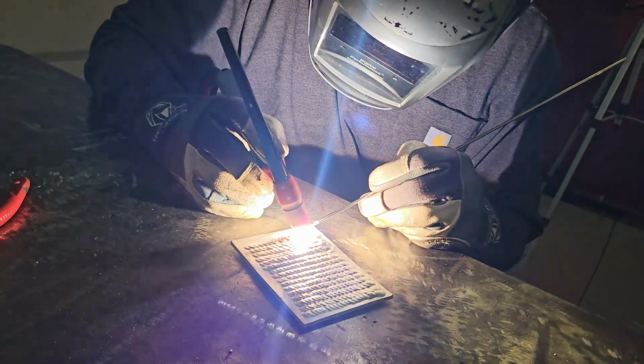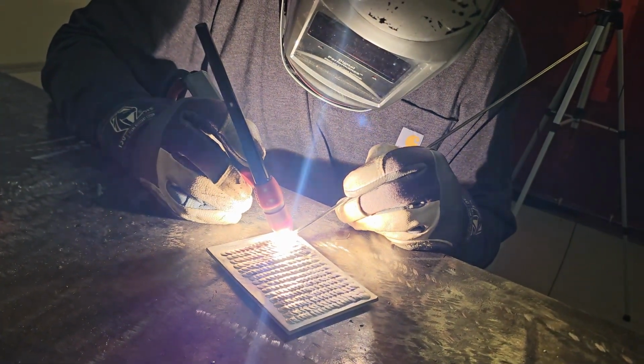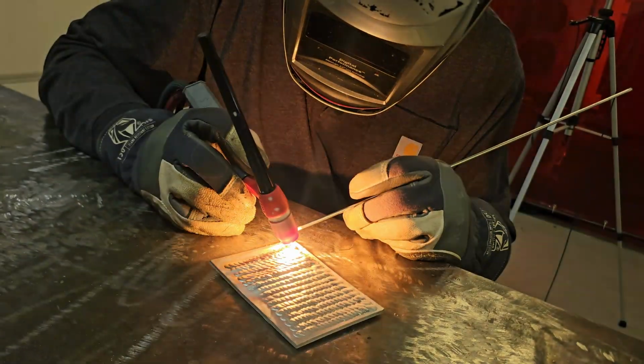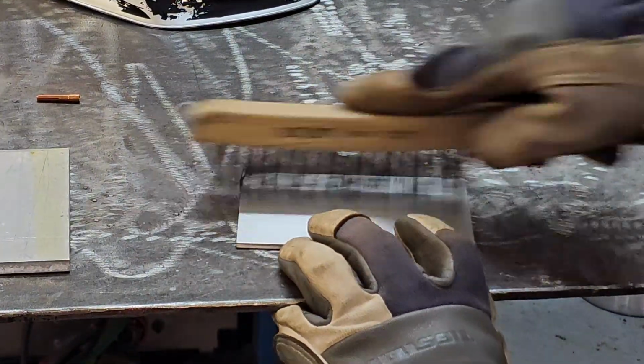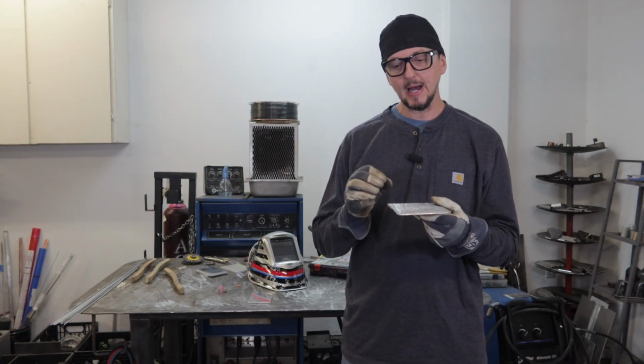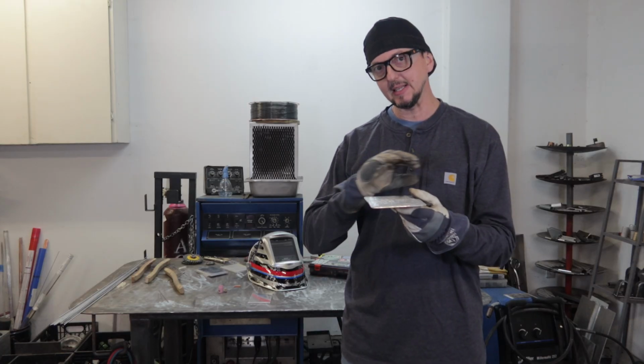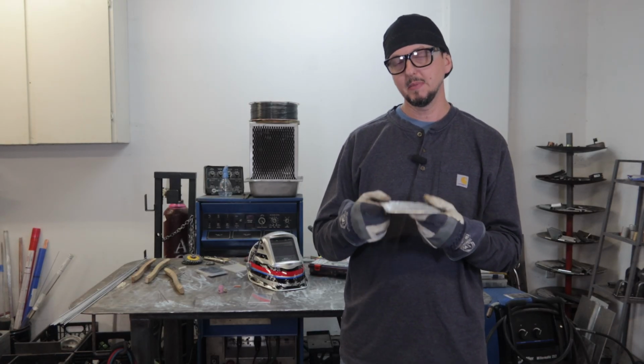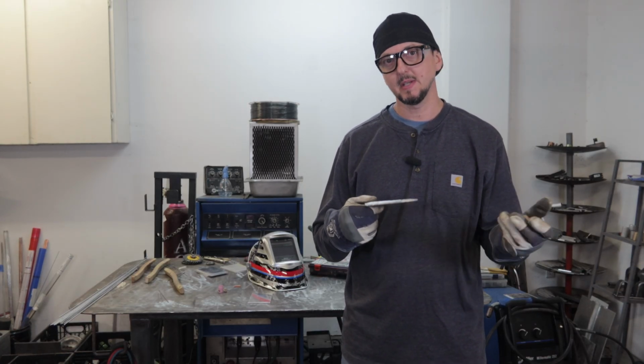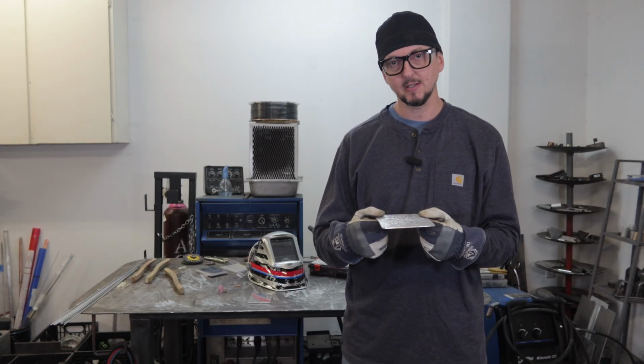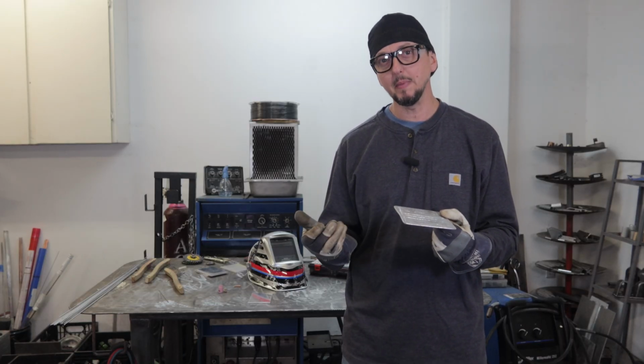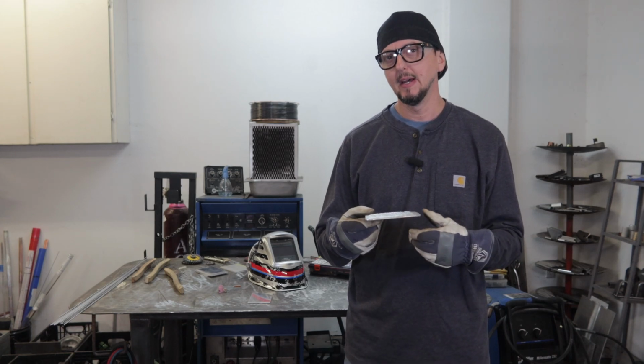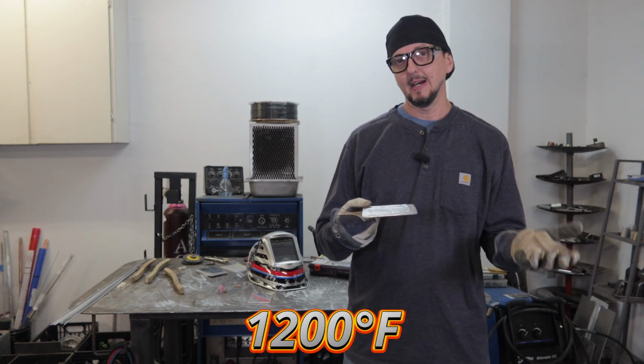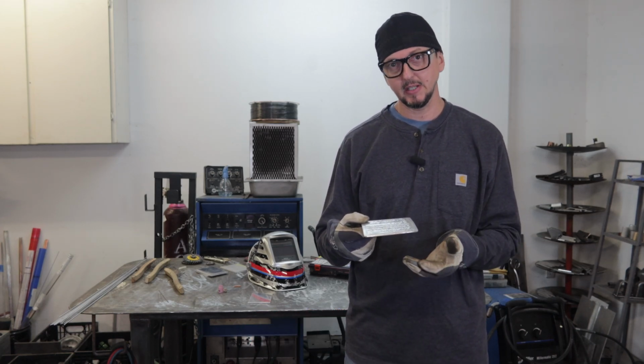There are a few things about aluminum that can make it seem difficult, such as the oxide layer, which we need to remove first before we weld aluminum. The high rate of thermal conductivity, meaning that the heat moves quickly through the material, which is very different from some of the other materials that we've been welding so far. It has a low melting point of about 1200 degrees. Compared to other materials, that's pretty low.